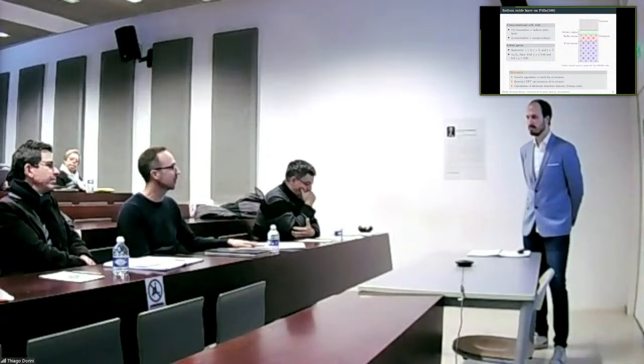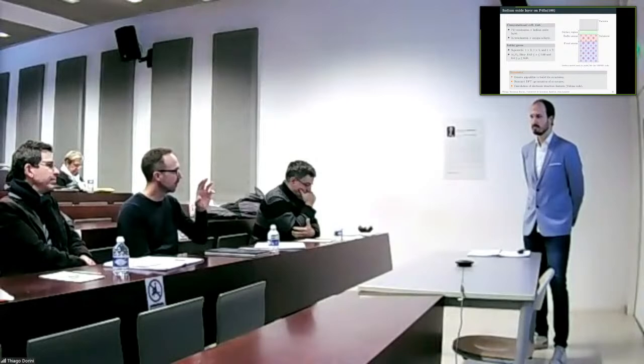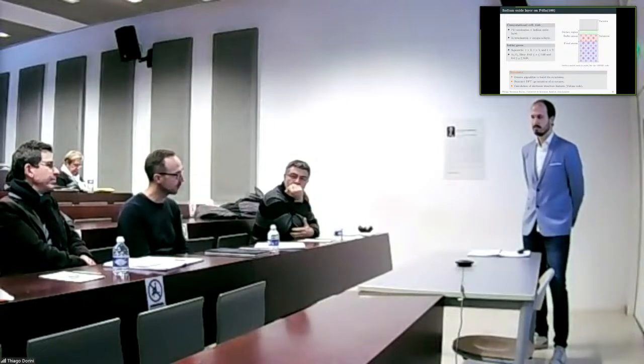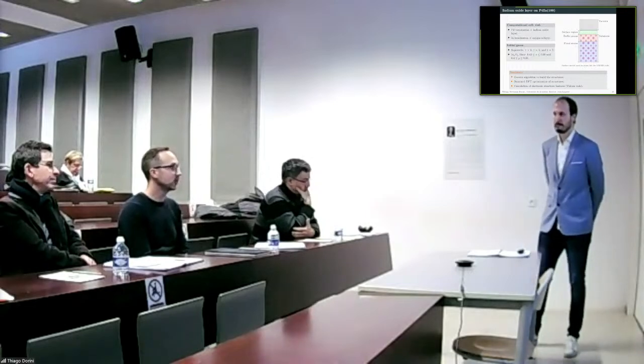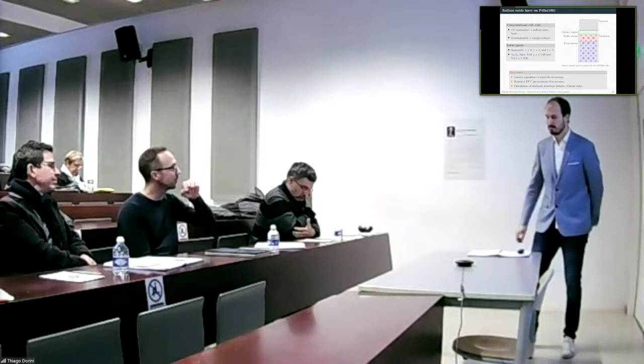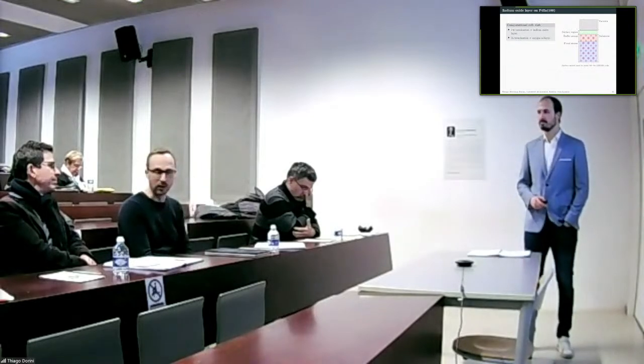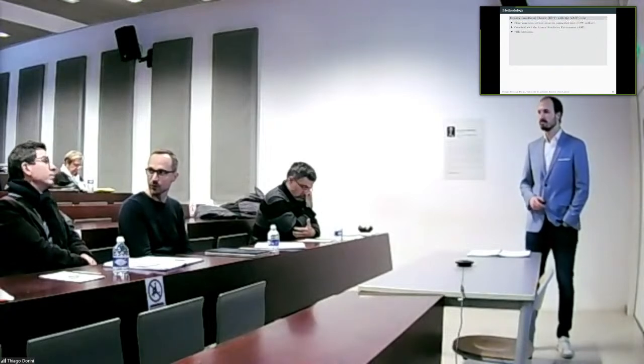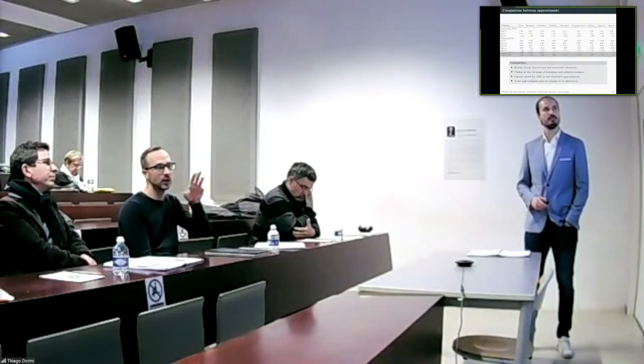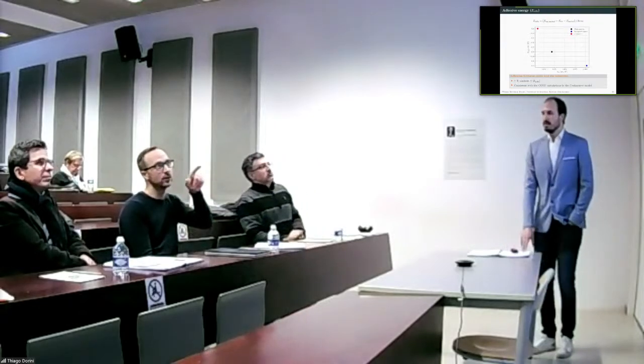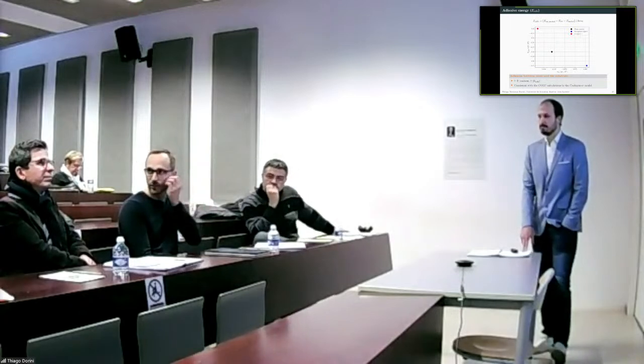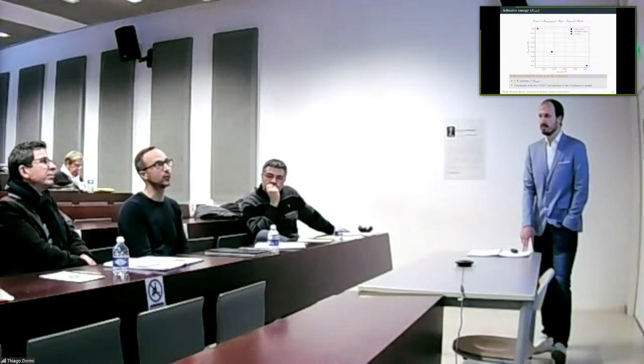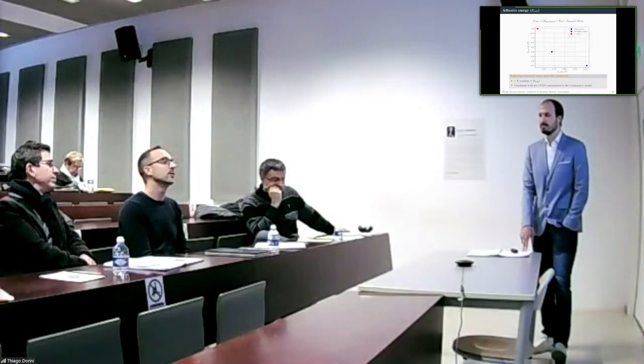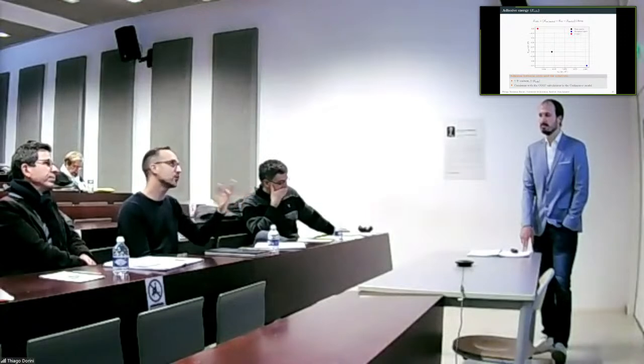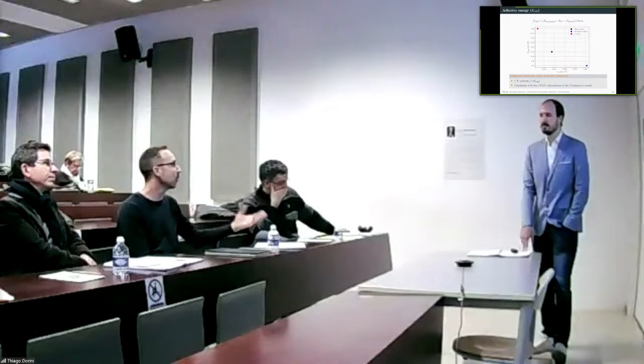And I think this is nicely discussed already in your thesis when you compare this square approximate, the strontium titanium oxygen system, with the hexagonal one that you found here. Because there you had a plot in which you go very much down with the adhesion energy, but the stoichiometries of the two are almost indistinguishable. You have strontium 0.36 versus titanium and oxygen 158 or so, and then it is strontium 0.38. So the stoichiometry differs within 1% or 2, but you go from the black one to the blue one. And the sigma phase approximant, then if you go to our own model, then it's natural why we are so bad in adhesion energy. It's just because of the low density of atoms.